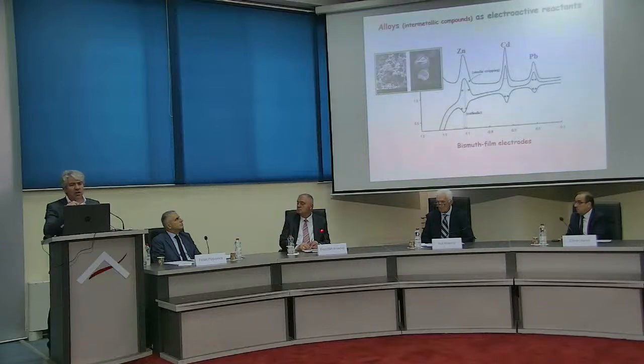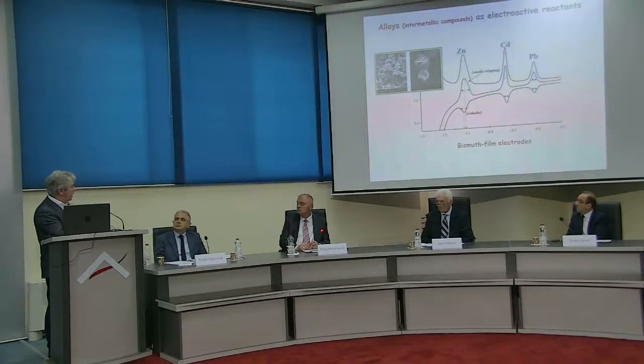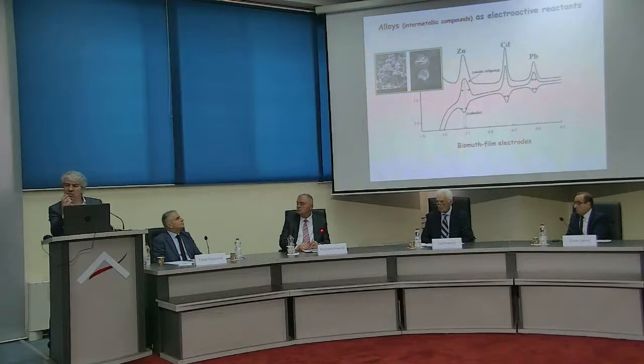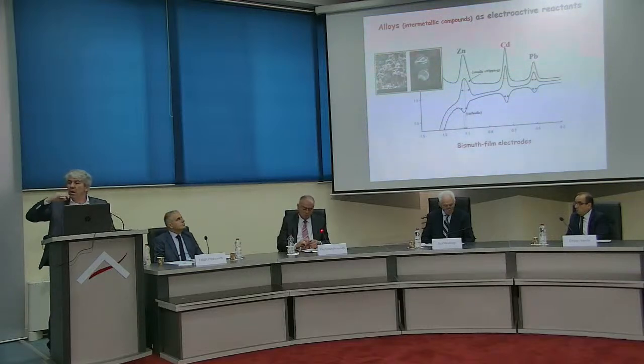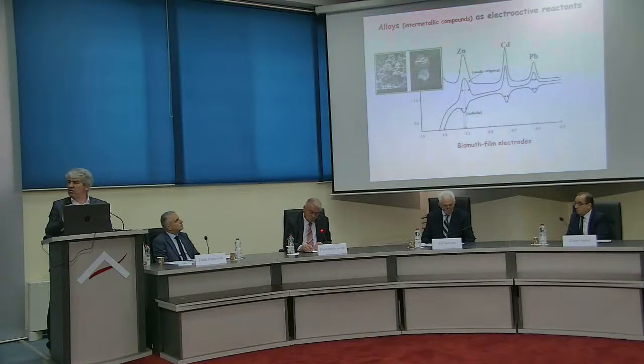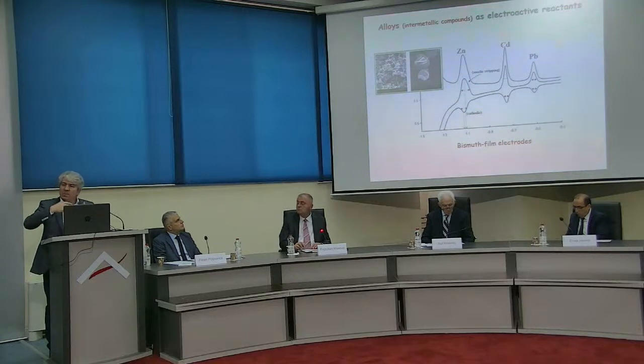In another branch of electrochemical science, not only solid crystals but alloys could be used as electroactive materials, or they can be used as a substrate for very sophisticated electroanalysis. For instance, bismuth film electrodes, in which the bismuth is electrochemically produced and deposited at the electrode surface, which then is used as a substrate for further deposition of traces of metals, zinc, cadmium, lead, and so on.